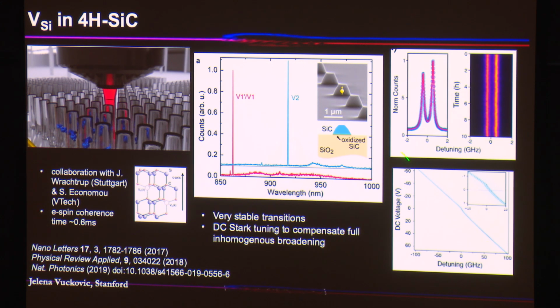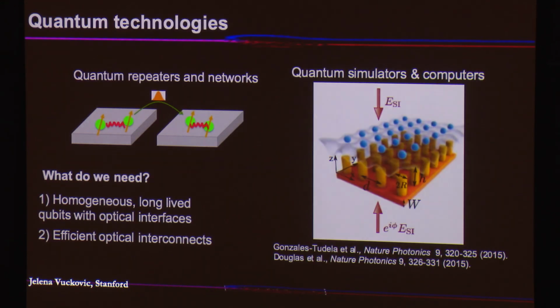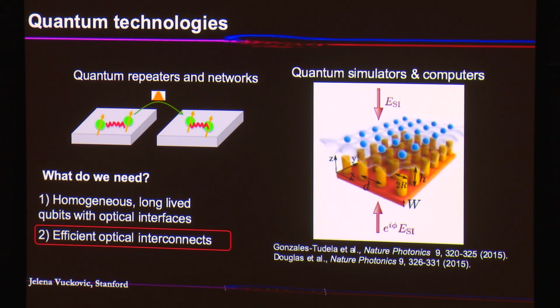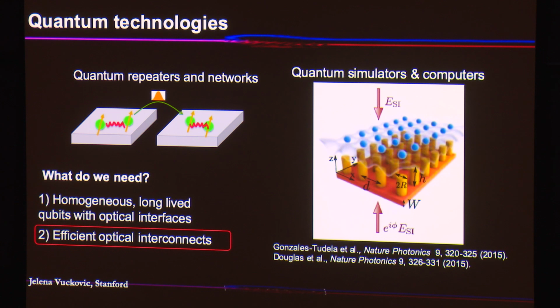And we've also shown that we can do Stark shifting with DC voltage, to tune it through the whole inhomogeneous broadening range of the system. So we can just put electrodes and tune these color centers individually in the system. But in the early work, we could only make pillars. Silicon carbide, like diamond, comes as a block of material, so we had to figure out how to make photonics. With silicon it's much easier: you order silicon on insulator, you make devices, and everything works out. But in these materials, it's not so easy. In order to connect all the qubits, you have to make photonics, and to make photonics, we have to figure out how to fabricate these materials and also how to design them.